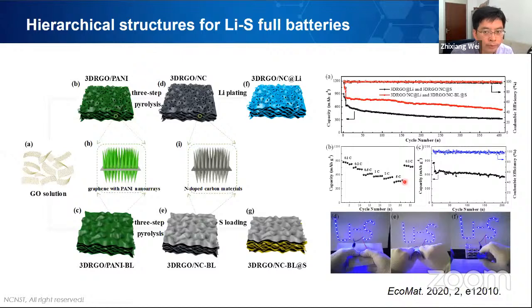With this strategy, we can produce different kinds of materials for different applications, for example, in lithium-sulfur batteries. For this structure, we can grow the polyaniline nanoarrays in these three-dimensional pores. And by thermal treatment like pyrolysis, we can get three-dimensional reduced structures of nitrogen-doped carbon. With this nitrogen-doped carbon, by filtration, you can change the vertical direction distribution. In this way, you can purposely design materials for the lithium metal or for the sulfur electrode.